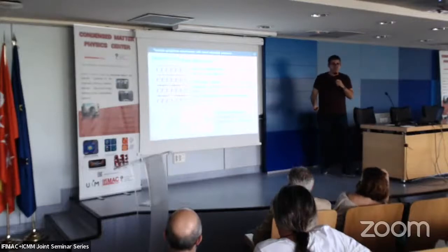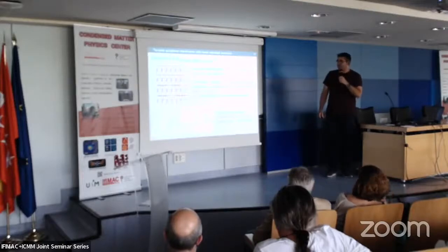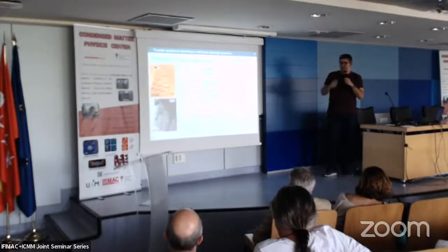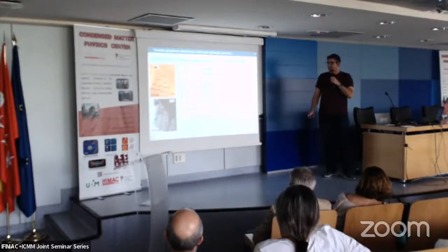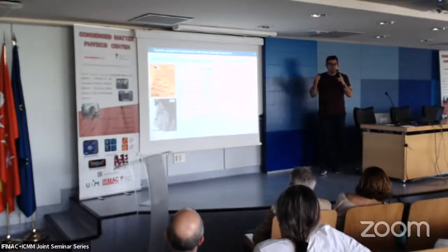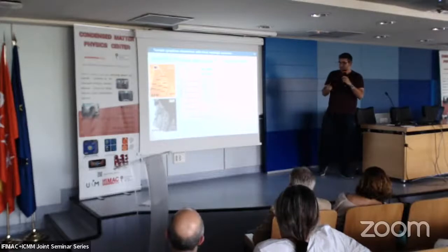Also from the simulations, for different configurations of the substrate, they found that the pressure needed to start this onset of covalent bonding is between 10 and 20 gigapascals. Again, in very good agreement with what we needed experimentally to start sinking our graphene and start to see this effect. Okay, again, we were very happy. This explained what we observed, but we wanted to see if indeed these bonds were appearing, even if in a very low fraction. So we prepared some samples to take them to the synchrotron in Trieste, because there the beamline where we went also had the beam focused to a very narrow diameter, so we can take photoemission spectra from very precise locations.